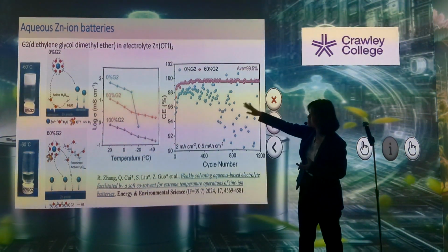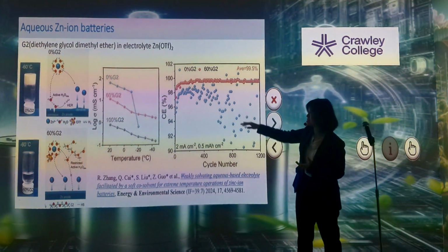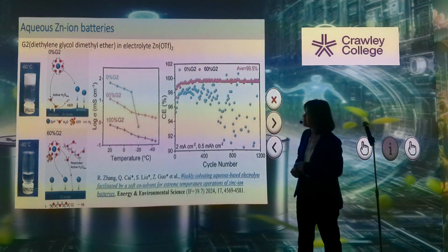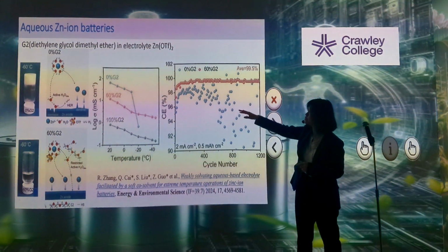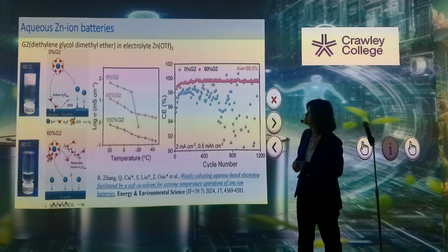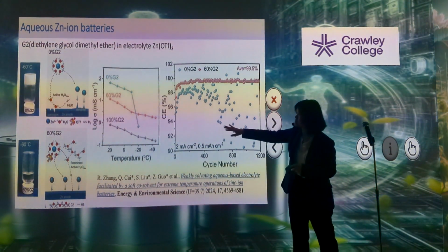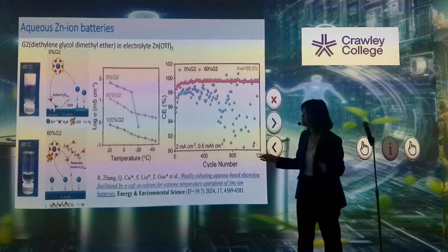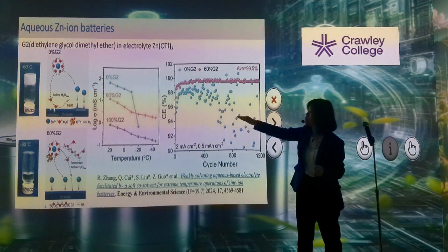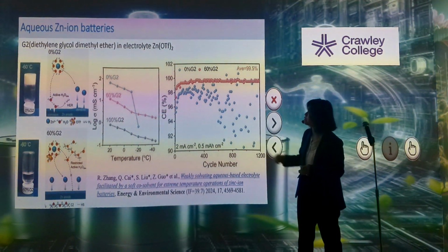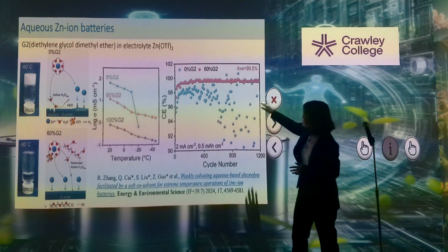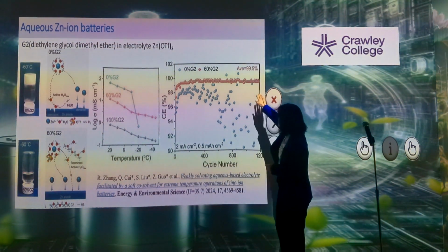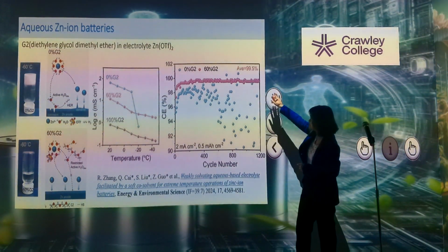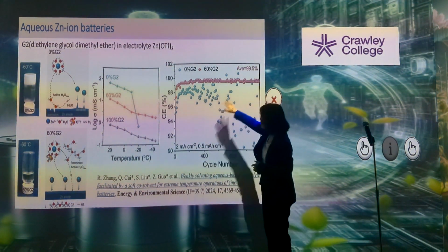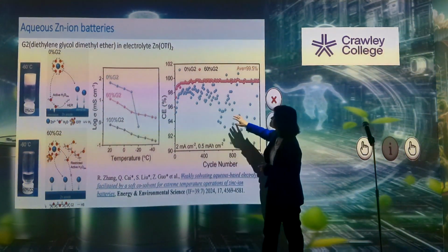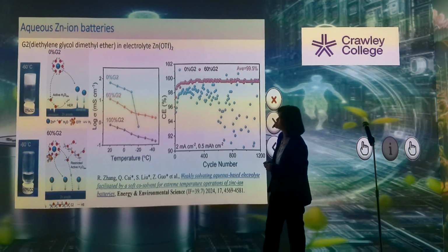And you can see there even at minus 60 degrees C, with 60% of that G2 molecule in the liquid electrolyte, the electrolyte still stays liquid, crystal clear. But without that G2 molecule, then it freezes and becomes solid. And it gives very stable performance, cycled up to 1,200 cycles, and much more stable compared to the other candidates, so the one without this G2 molecule.